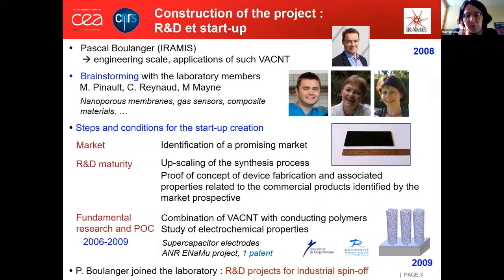And it turns out that this identified market combined very well with our first approach in terms of fundamental research regarding a new concept, which was to embed such aligned carbon nanotubes in a conducting polymer. So basically, these aligned carbon nanotubes were used as templates to cover them with electronically conducting polymer. This polymer gives the pseudocapacitive capacitance of the system, and the nanotubes give rise to a very high surface, which gives the polymer high availability for the electrolyte.